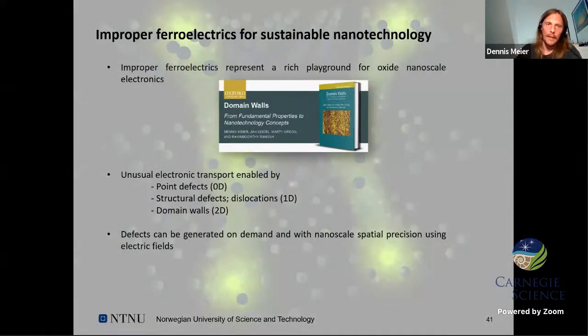But to wrap up, I hope that I was able to convince you that improper ferroelectrics are a very rich playground for discovering new physics, and that we can really generate unusual electronic responses at the nanoscale by playing with the point defects, the structural defects like dislocations, and the domain walls, and that these defects can really be generated on demand and at the nanoscale.